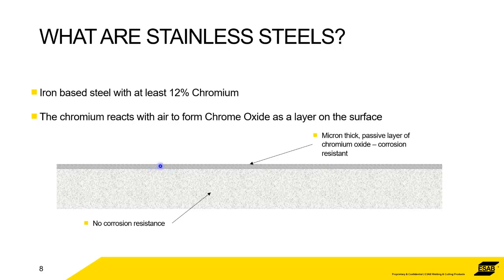If this passive layer, we're talking micron thick. I mean, on this diagram it looks millimeters thick, but it's microns thick. If the passive layer is removed by any method, abrasive or by accident of some kind, if the base metal still remains in air, then it'll reform, it'll regenerate. So there's sufficient chromium in there to create chromium oxide on the surface, and that's exactly what happens.